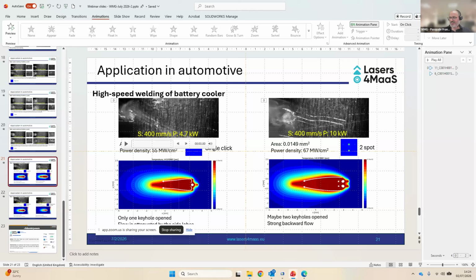Let's say again, it's a baseline, because we know what's happening from other people, from other companies, including other laser vendors and machine builders. Those plates are aluminum 5754. Some people I know are using nitrogen as a shielding gas. However, the welding speed is in the range of 150 to 200 millimeter per second, which is okay, because you can attach a shielding gas nozzle on the end effector of the robot and move it around. The problem is if you start going much faster, more than 600, even 800 millimeter per second, using shielding gas becomes a bit too complicated.